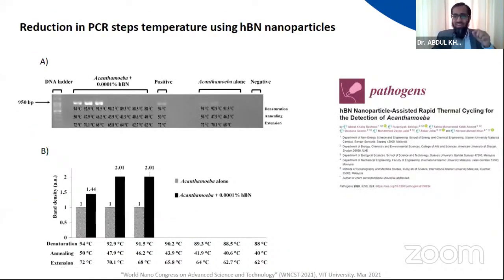One of the key issues with PCR is the duration, the time it takes. So first thing is the yield itself. We have already established clearly that the PCR yield can be improved significantly, almost 10 folds or even more. Now, what you see on the screen is that not only can you enhance the yield of PCR, so the DNA is yielded much higher in quantity, but you can also reduce the temperature of the 3 PCR steps, the denaturation, annealing, and extension, which happen at a particular range of temperature. When you have nanoparticles incorporated in the liquid, the specific heat capacity of the liquid will go up, and as a result, you don't need to heat the PCR reagent at 94 degrees, which was the case without the nanoparticles. Now you can achieve denaturation, for example, at 90 degrees or 89 degrees or even 88 degrees. So this was established very clearly.